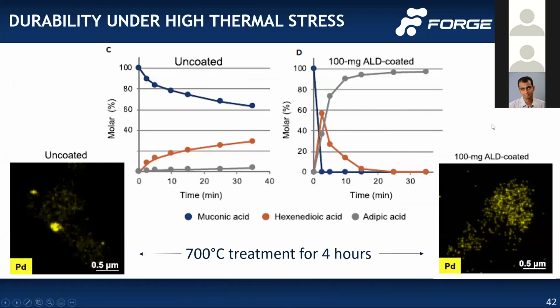This is the same study, same work, with thermal treatments at 700 degrees C. This is showing something similar to Jinhua Liang's work with platinum, except this is for palladium, showing the sintering. At 700 C for 4 hours, palladium sinters without an overcoat, versus with an overcoat you maintain the dispersed palladium on the surface. And because you're maintaining that dispersion, you're actually maintaining your reactivity.